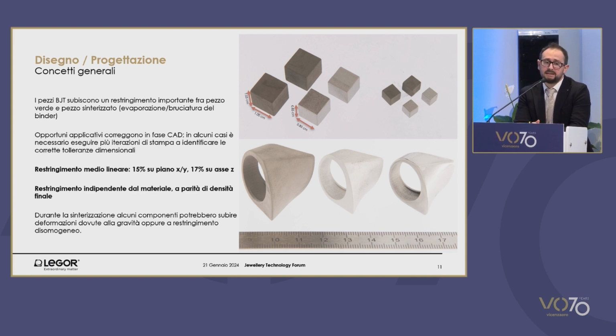Design and drawing. One of the most important aspects of binder jet technology is that in all intermediate phases prior to sinterization, I have an aggregate of metal powder and binder. A polymeric binder that is used in a much smaller quantity compared to other additive technologies such as MIM. Here we have approximately 1% of the weight of the material. I still have to consider the shrinkage in time due to the fact that my initial item has a certain size during the drawing and designing phase that must be bigger due to the fact that there is the binder as well.